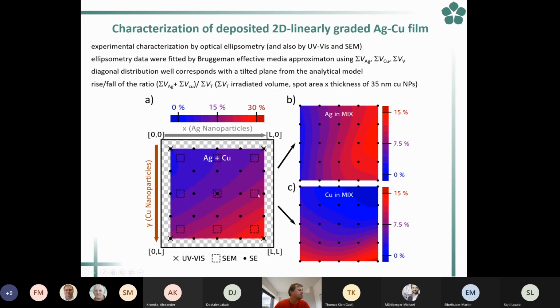of the substrate we have a different chemical composition, and we were able to tune the chemical composition, but also the size of the nanoparticles. And then according to that, we were able to tune and manipulate these absorption peaks.